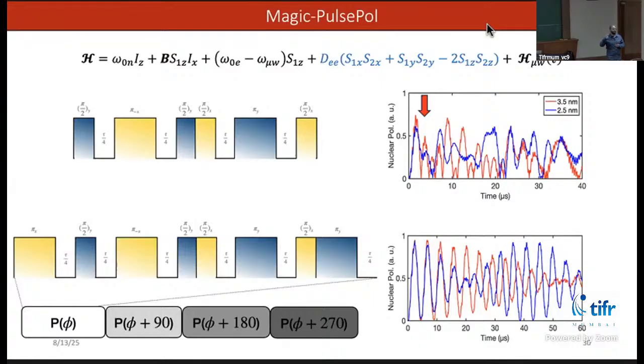Since in CW, we cannot have more than one frequency, we cannot have more than one phase, but in pulsed, you can change the timing, you can change the phase, you can change the amplitude. So this technique is based on, if you see, these are all the pulses. Every colored bar is a pulse with different length, with different phase. I see. Okay. But I would have assumed that it would be the same for continuous wave as well. I mean, if you put two electrons, the transfer will go down. It's different because if you are doing it continuously, you always have one Hamiltonian, but here we have constructive and destructive Hamiltonians. We can select something and we can cancel something in the pulse technique. In the CW technique, it's not easy to do that.